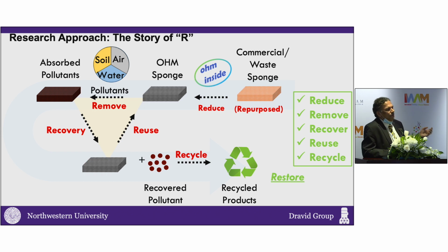And then you remove the pollutant, as in the case, as I showed you with oil, you just squeeze the oil out, and it's very selective. So less than a few percent of water goes in. Normally that would be a big problem, because if you have an oil and water mixture and you're resulting in an oil and water mixture, you still have the same problem. But here almost 95+% is recovered as oil, and that gives us only 5% water. So you recover that and you reuse it.